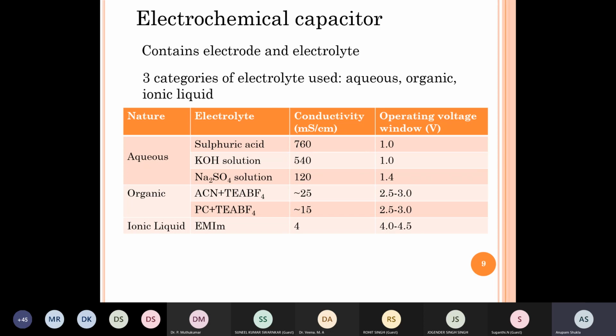Okay, now all of these electrochemical capacitors essentially contain two electrodes and an electrolyte. And the electrolyte is one of the problematic parts of the electrochemical capacitor. It is an essential part, but it also presents problems. One of the biggest problems with the electrolyte is its conductivity. Its conductivity is much smaller than the electrode. So in an electrochemical device, the resistance of the device is primarily determined by the electrolyte.